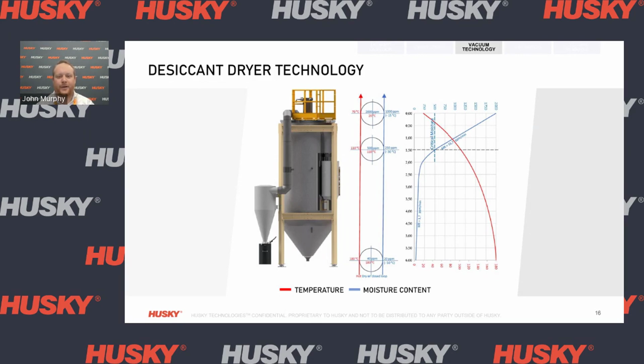When we look at humidity level, we can see that we have a linear line to start off for the first hour and a half of the material being in the hopper. This is where we're able to remove that easy to remove moisture from the pellet at 100 degrees Celsius. However, after around 1.5 hours, we do reach a critical moisture level where now we have to remove that tough to remove moisture that's internal to the pellet. We can see a sharp drop off in the desiccant dryer's ability to remove this moisture. It takes the remaining 4.5 hours to get down to below 40 ppm of moisture.